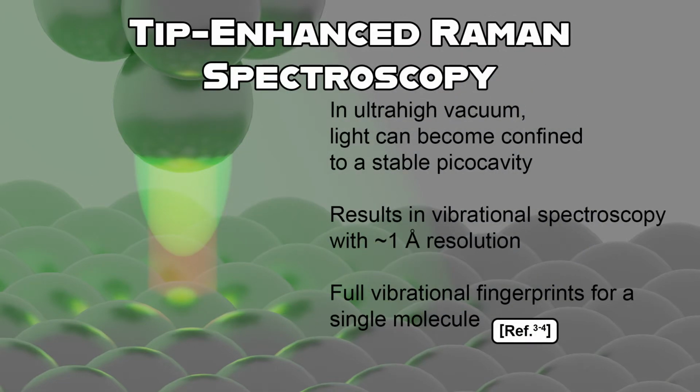Implementation of TERS in ultra-high vacuum can yield spectroscopic information with Angstrom scale resolution. Light becomes confined to a picocavity, leading to about 1 angstrom resolution and enhancement factors of up to 10 to the 12th and 10 to the 13th. This results in the ability to obtain full vibrational fingerprints for a few molecules, or even a single molecule adsorbed